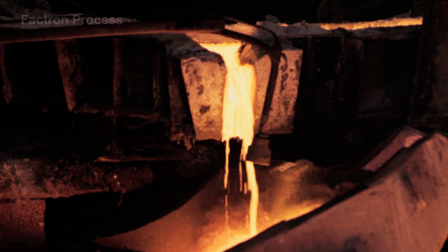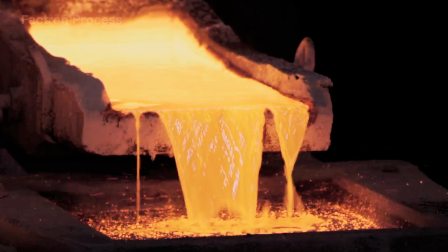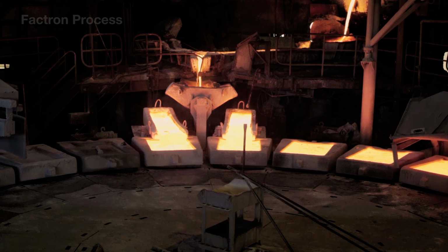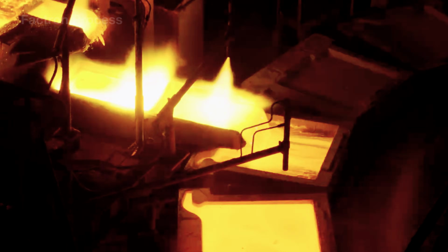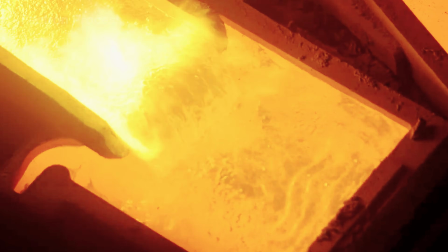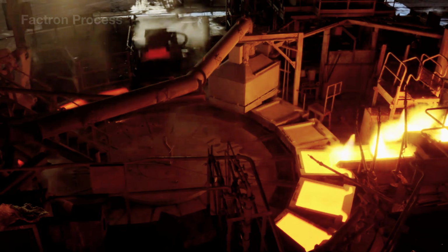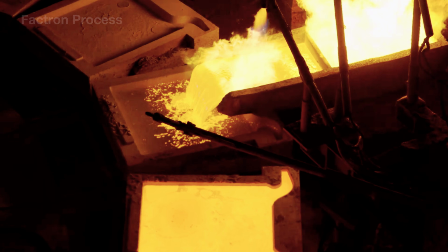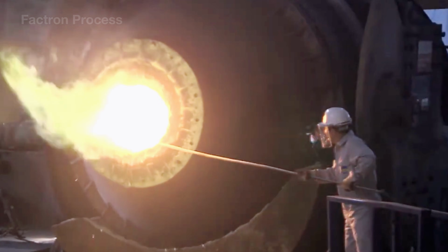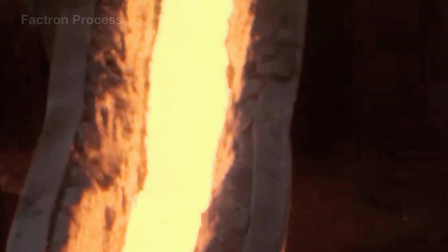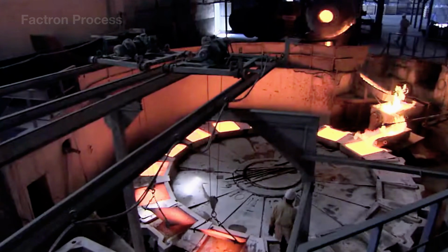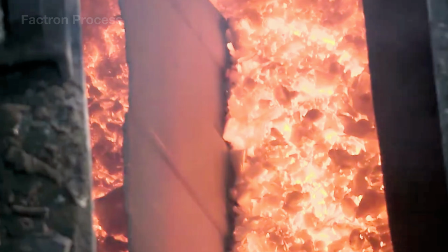Workers continuously monitor the inside of the furnace and operate specialized equipment to remove this slag, allowing the molten copper underneath to become increasingly pure. Once smelting is complete, the furnace tap is opened, allowing the molten copper to flow through channels into the casting system. Here, the copper is poured into large molds and solidifies into crude copper plates with a purity of approximately 99%. For the first time in the entire journey, copper no longer exists as a mineral mixed inside rock, but has become metal plates ready for the next refining stage.